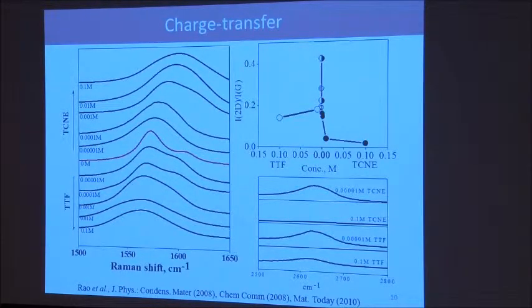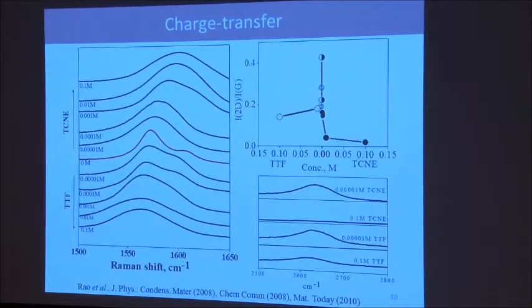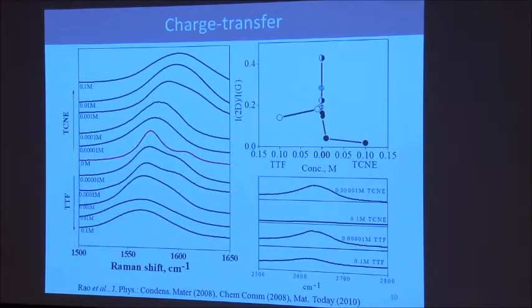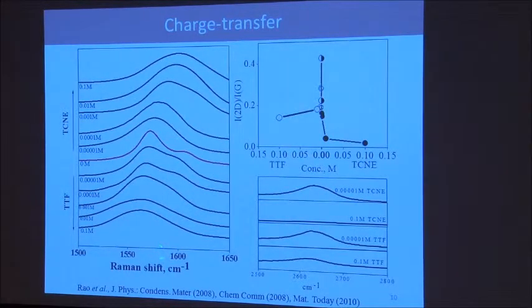Graphene, you can make a transistor out of it, a field effect transistor. You can dope electrons and/or holes in it by electrochemical means. The same thing you can also do by putting a molecule on it. If you take graphene and put on its surface an electron donating molecule like tetrathiafulvalene, or an electron withdrawing molecule like tetracyanoethylene, you can see shifts in the Raman band. The Raman G band shifts to higher frequencies when you withdraw electrons, and lower frequencies when you donate electrons, showing it is highly sensitive to p-type and n-type doping, even by molecular interaction and charge transfer.